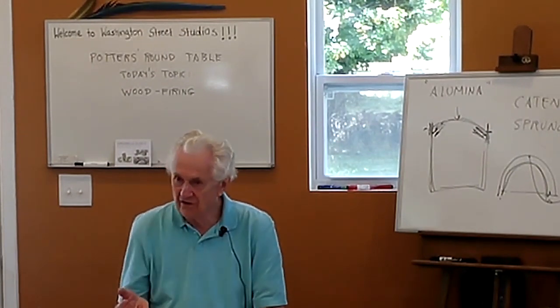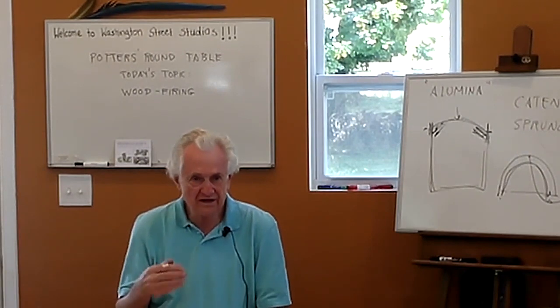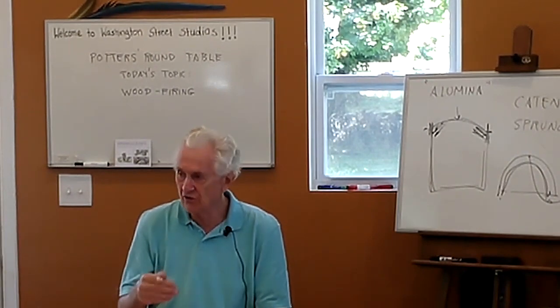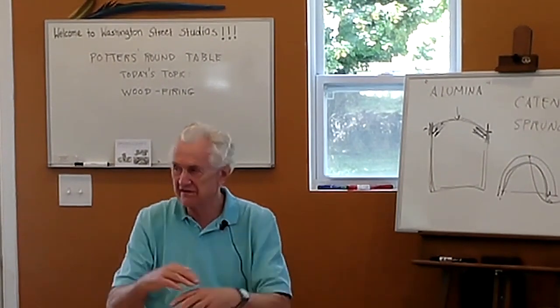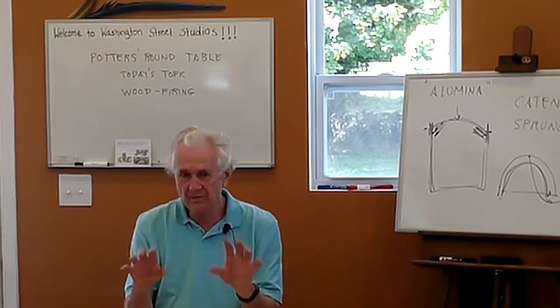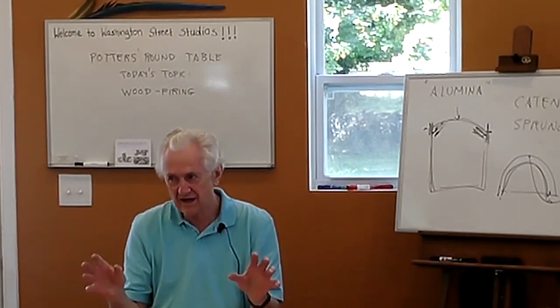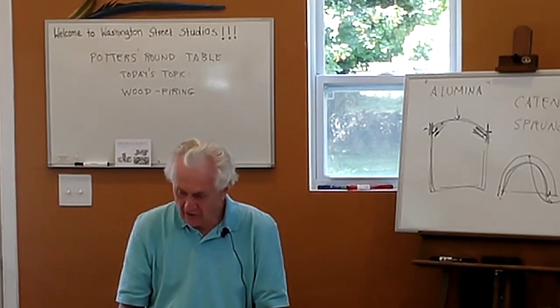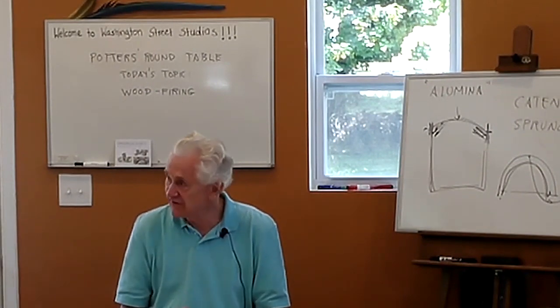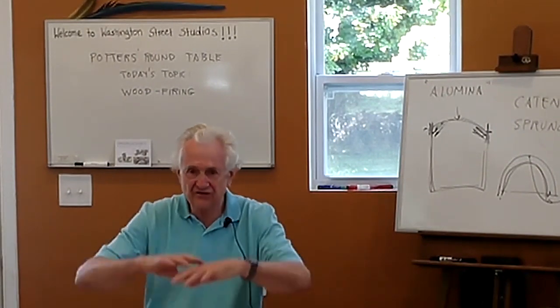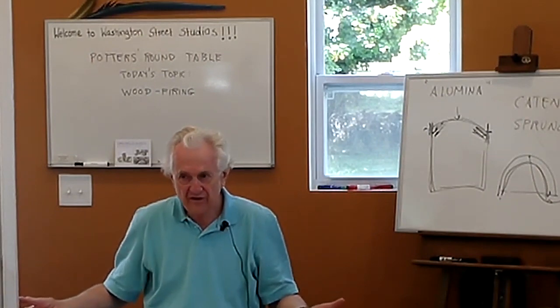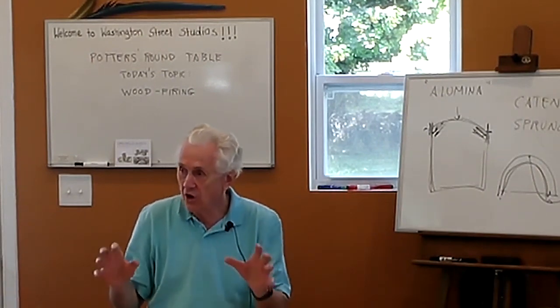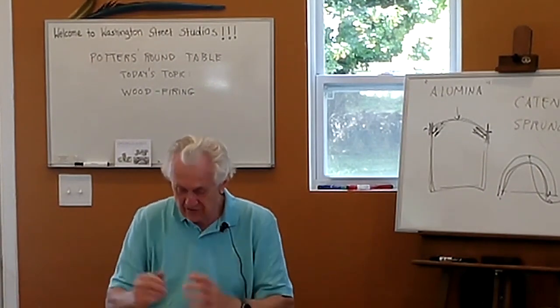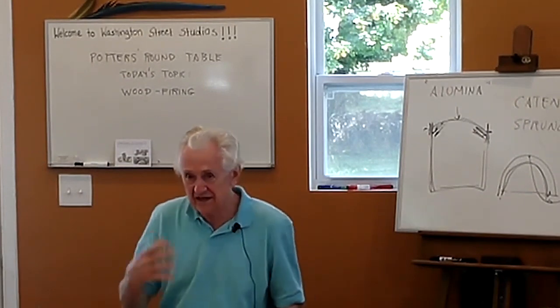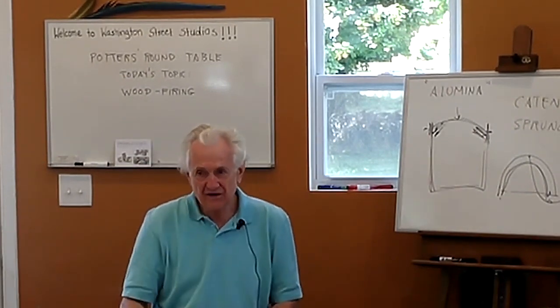In order to fire a wood kiln efficiently and properly, you need to control the air. You don't just let in any amount of air that wants to go in. You have to have openings that you can control, to increase the amount of air or decrease it. And so that's another important feature of kiln design. You don't just have an open area where the air can just rush in. You have to have openings that you can close or partially close to control it. And all of those affect the heating rate and the amount of reduction you get.